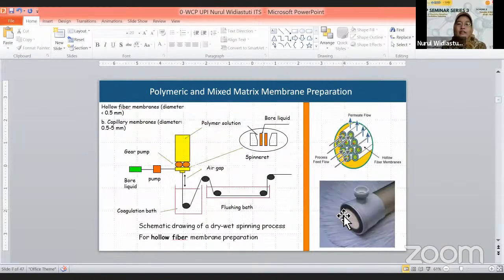And a different kind of module is called hollow fiber membranes. Hollow fiber membranes have a diameter of less than 0.5 millimeters, and there is another kind of these membranes called capillary membranes, with a diameter a bit bigger than the hollow fiber membranes, which is 0.5 to 5 millimeters.